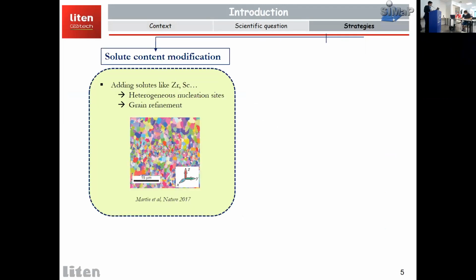So now several strategies can be thought of to solve the problem of cracks. For example, the first one can be the solute content modification, which is very much reported in literature, like adding zirconium and scandium to induce heterogeneous nucleation sites, and basically this gives you grain refinement, and this leads to cracking mitigation.